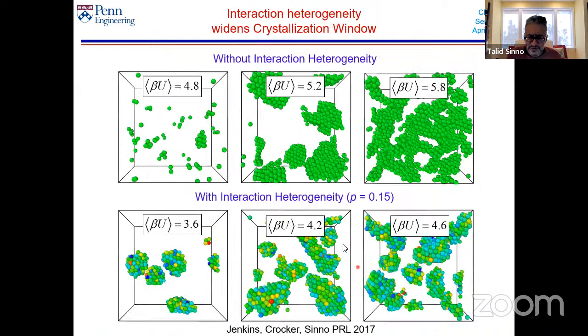So given the limitation on time, I'm just going to go straight to this. So this is 3 sets of simulations at 3 different interaction strengths. What I'm showing you are only the particles that are bonded to other particles as part of clusters. If I have an interaction strength, and these numbers don't mean anything, of 4.8, it's subcritical, which means most particles aren't clustered. When I increase it slightly to 5.2, all of a sudden I form these big crystals. When I go to 5.8, the whole system just gels up and I form these crystalline gels.